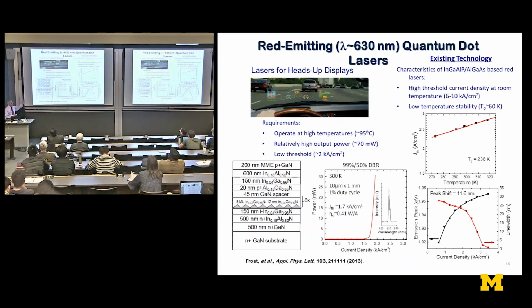Then we followed it. We went even further. Now, nobody had gone to red in the nitrides. So this was the first venture into red, and these are red lasers. You can get very decent amounts of power. This was all done by student Thomas Frost, and we had a contract with Denso, Toyota Denso, to demonstrate that these lasers could give sufficient power, show temperature stability of the threshold current, and work at high temperatures. And we showed operation up to 95 degrees centigrade. And the thresholds we are getting were lower than what they had stipulated. So now they have taken it over, and they are developing this in Japan for heads-up displays.